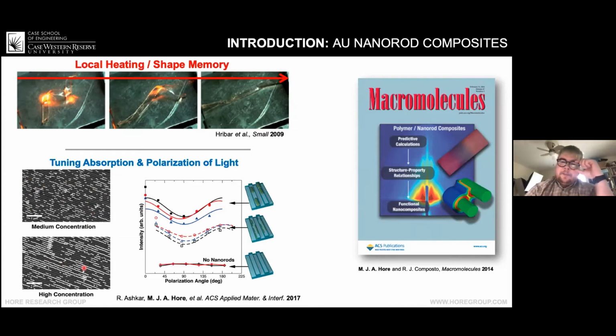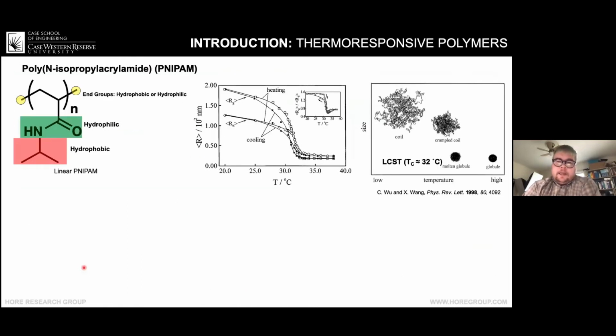So the point that I'm trying to make here is that the dispersion of nanoparticles and the morphology of that dispersion within a material is of great importance for the physical properties. We can even go one step further, and look at something like NIPAM that we've studied in solution. This polymer is quite interesting because the monomer has this hydrophilic region as well as this hydrophobic region. And as I showed earlier, you can tune the end groups of the polymer chain, and those properties are going to impact its thermal responsiveness.